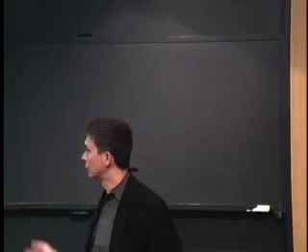And so this was one of those early calculations where they did exactly what we showed here. Build a cluster expansion, parameterize it with density functional theory. In this case, did Monte Carlo to do the statistical mechanics to find a temperature, and essentially get this calculated phase diagram. And there's the equilibrium phase diagram, but then you can also do the metastable. This is the delta phase precipitate by essentially removing the free energy curves of the stable phases and looking at them. The liquid was kind of empirically added, I think, to this calculation.